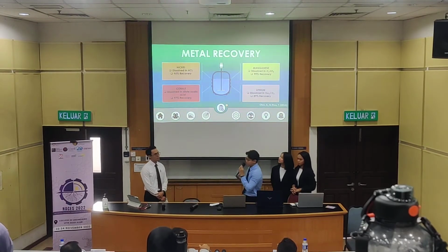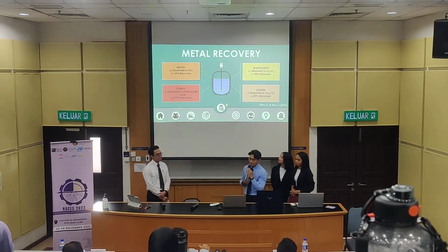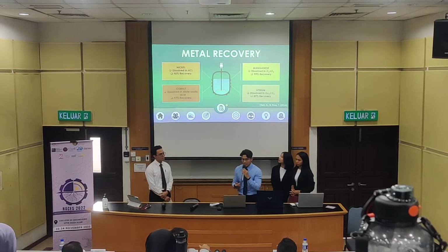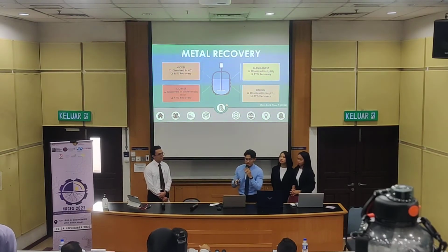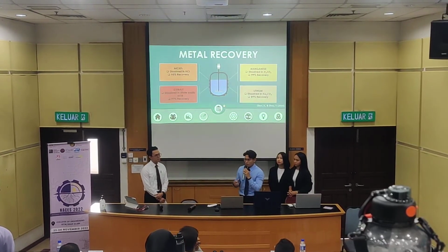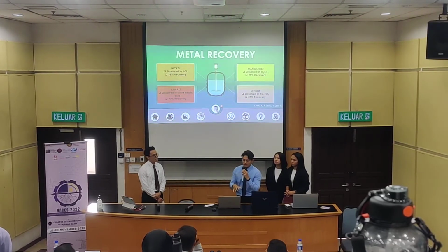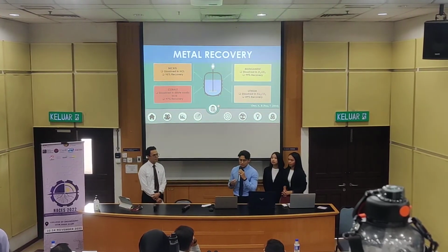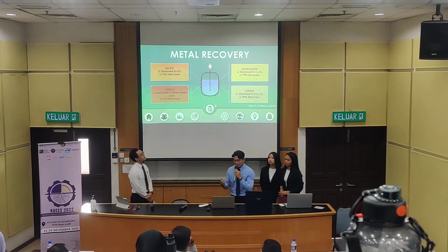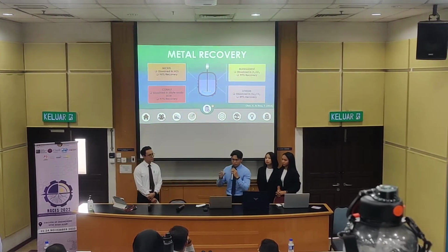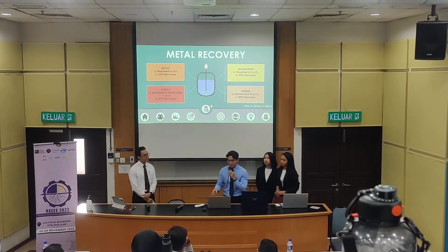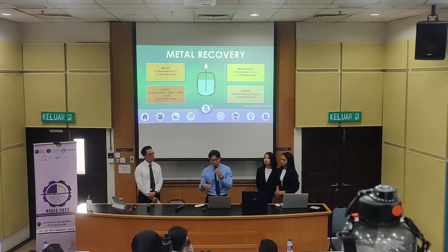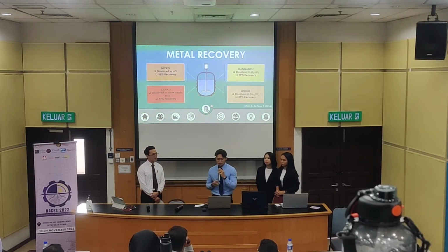For nickel precipitate, it will be dissolved in a hydrochloric acid solution and will achieve around 95% metal recovery. Meanwhile, for cobalt, it will be dissolved in dilute oxalic acid and recover around 97% metal recovery. And then for manganese ion, it will be dissolved in sulfuric acid and achieve 99% metal recovery.